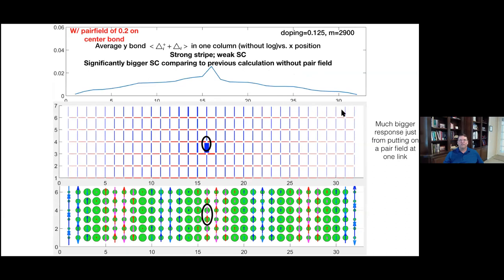Okay. But just to give a little more texture to that, we get a different result if we do the measurement where we apply a pair field operator on one link and look at the response to that. Generally we think that this is a more accurate result. And now this curve here is not on a log scale. This is just showing the bare results, and you see a much bigger response.